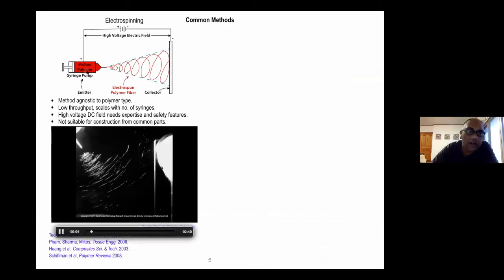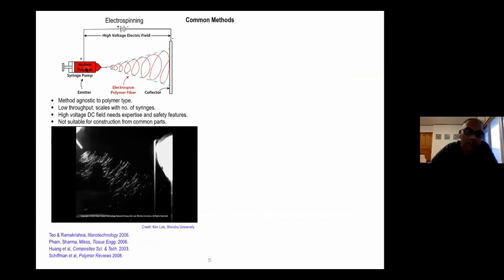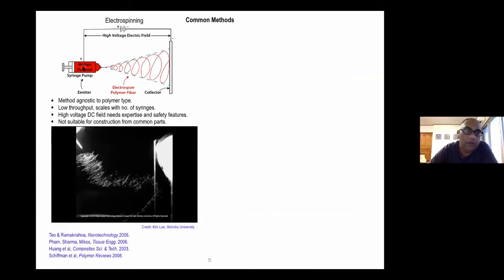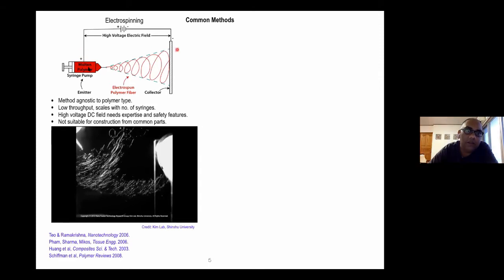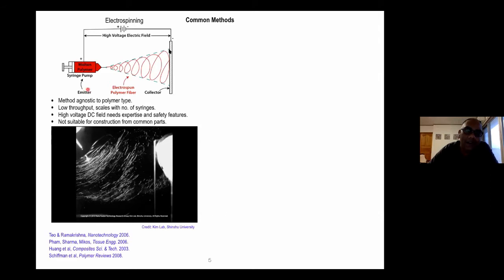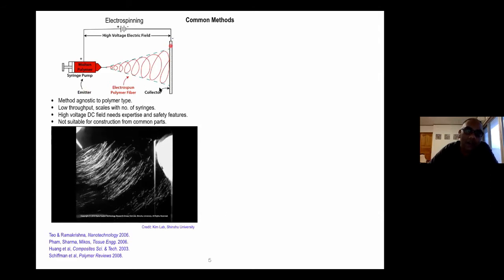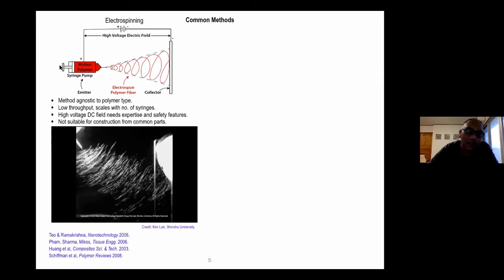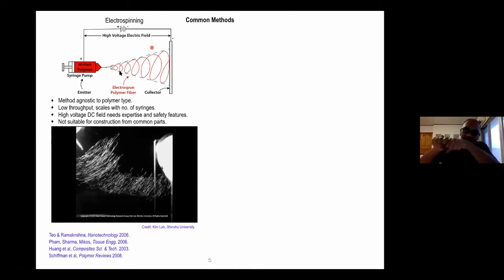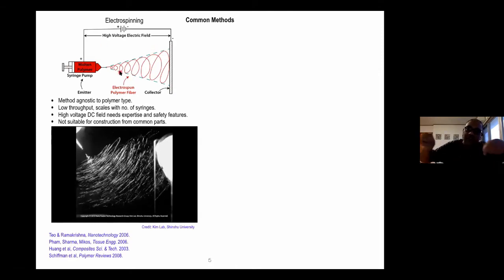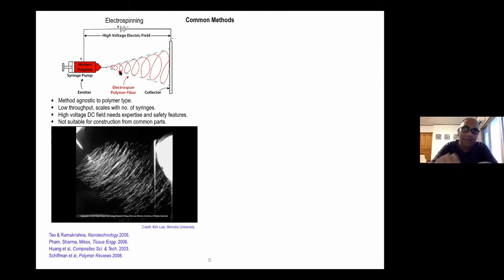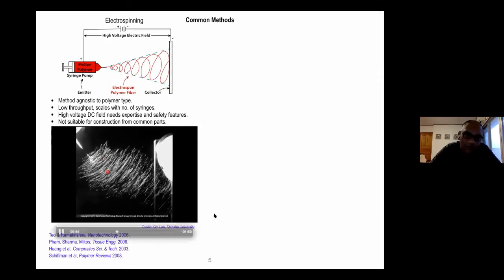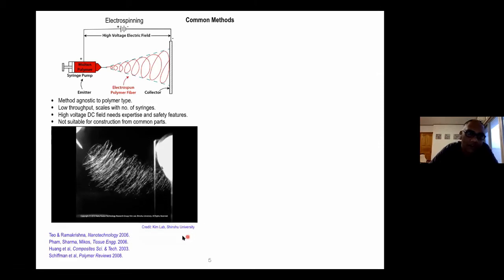In this, you have a syringe pump in which you load either a molten polymer, which is more rare, or usually a polymer dissolved in an organic solvent, and it is pumped out. You apply pressure and you generate a drop, and you apply a high voltage electric field between the syringe pump, which I call the emitter, and a drum or a plate held some distance away, which I'll call the collector. The pressure head from the syringe pump initiates the jet, and once it emerges, the high voltage electric field accelerates it and stretches this non-Newtonian fluid. So it is basically undergoing a case of extensional rheology. I'm showing this video that I have borrowed from a group at Shinshu University in Matsumoto, Japan. It's beautiful to look at.